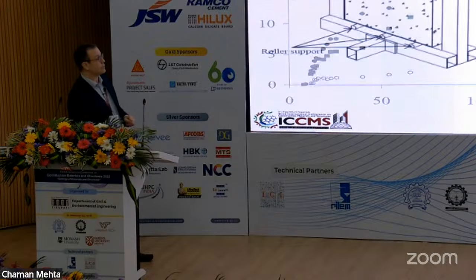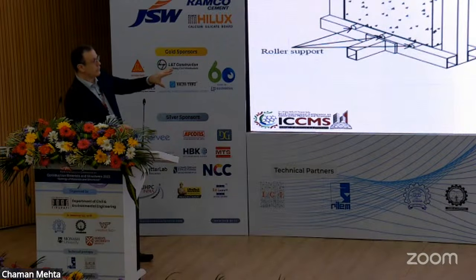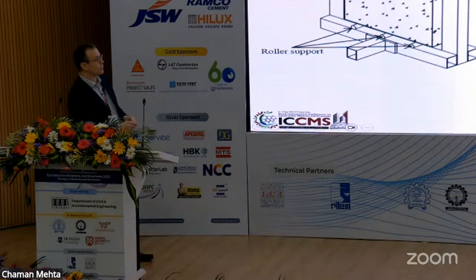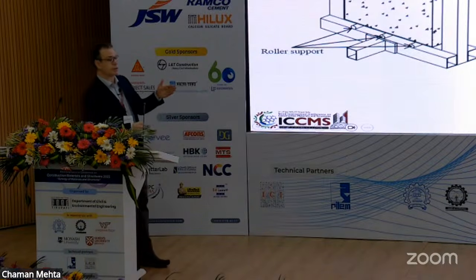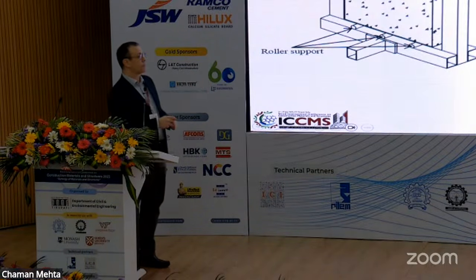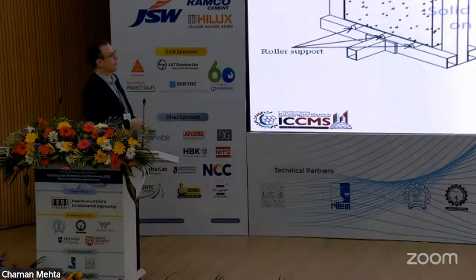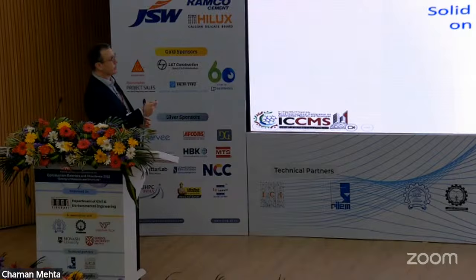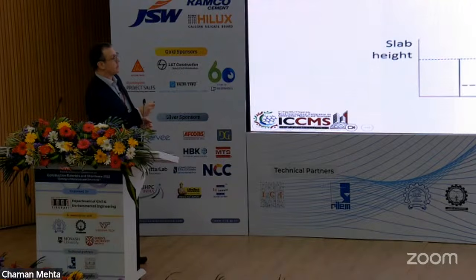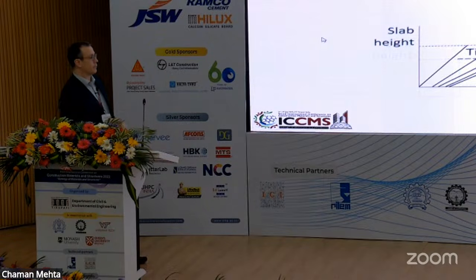What we did here was also to isolate and try to predict these behaviors by putting different surface conditions on the unreinforced concrete samples, kept there over time. It has to do with actual drying conditions: when you dry from the top and bottom, or just from one side. If you dry from top and bottom, you can have a shrinkage profile of this kind. In reality, for design purposes, you can approximate it as a linear, constant deformation, which reflects the total deformations you will have in a sample if you look at the monitoring.